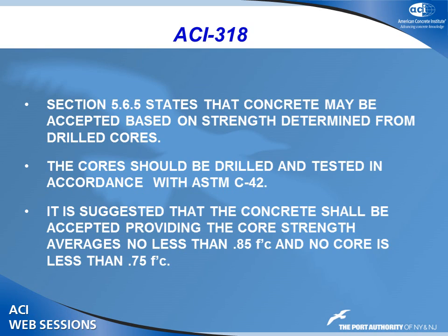And again, ACI says that if the core data is at least 85% of f'c, they would recommend accepting it, and if no core was less than 75%. And again, I don't really have an issue with this. The only reason why we started coring more is because some of the engineers that we had working for us would take the core data and divide it by 0.85, and I'm not sure if that's accurate at all.